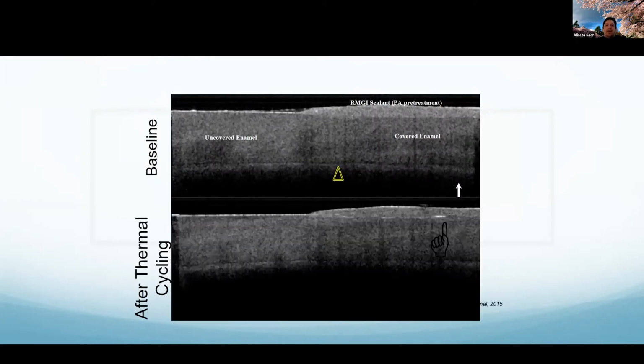However, when we look at a lot of these sealants, we see that there is an increased chance of interfacial failure. This is without air abrasion, but even with abrasion, there is an increased chance of interfacial failure with aging. So basically, whether you're doing Glass ionomer or you're doing a resin-based sealant, you have a higher chance of interfacial failure after a few years, after a few months. So what is the right thing to do in these cases? And that's what OCT shows. So here's your RMGI-based sealant, okay? We did phosphoric acid pre-treatment. It's very pretty clean enamel because this was polished enamel. And then after a couple of 100,000 cycles, you can see that the RMGI is debonding or separating from the enamel surface. That's not good news for a sealant, right?